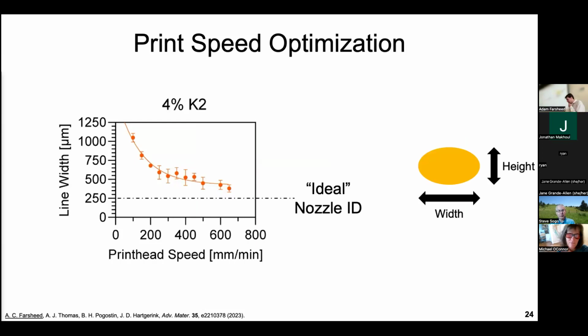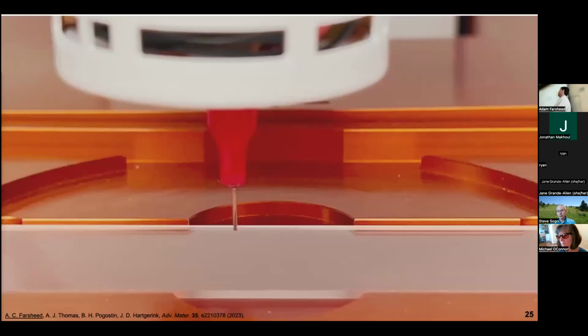And so I just want to quickly call to your attention that the ideal line width that we should be able to achieve is the inner diameter of the nozzle that we're printing out of. And in this case, it's 250 microns. But unfortunately, we're not able to reach that kind of ideal case before we see line breakage. And that's because our hydrogels that we're printing are not actually going to be perfect cylinders, but they're going to be sagged a little bit. And so the height is going to be shorter than the width. And we're going to be kind of limited in that sense. And this will be a concept I come back to much later in the talk.